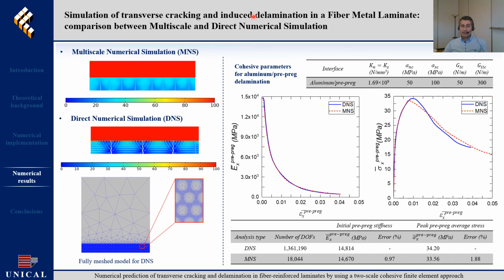On the one hand, the good accuracy of the proposed method is demonstrated by the very small percentage errors on the initial stiffness and the peak strength of the prepreg layer. On the other hand, its notable computational efficiency is attested by the very high ratio of about 75 between the number of degrees of freedom for the reference direct analysis and that for the present multiscale analysis.